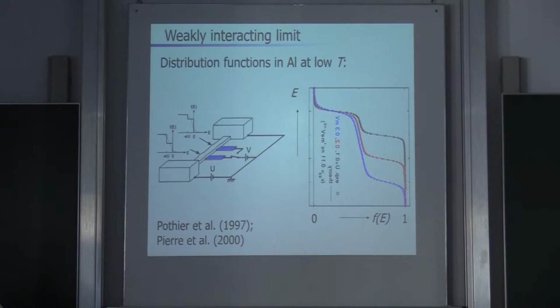So there is not a thermalized distribution in the system. That means the whole concept of the spin accumulation in terms of Fermi-Dirac distributions is absolutely not rigorous. So we should assume that these temperatures, these parameters, are some sort of parameterization of something which might look very different. For example, if you look at this curve, you could say, let's describe it by a Fermi-Dirac distribution function which looks like that. It does not have this double step, but it effectively describes this smearing out of the distribution function, and we can take that as an effective temperature. Exactly the same we should assume with this electron distribution function. We do not know how they are distributed, but we can parameterize them by some effective broadening and center of the Fermi-Dirac distribution function.